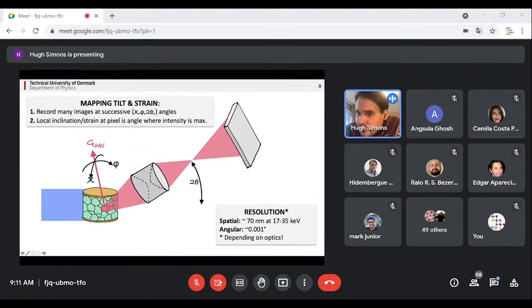And right now we have a spatial resolution of something like 70 nanometers at between 17 and 35 keV. And we have an angular resolution of about 0.001 degrees. This all depends on optics, but I would say our spatial resolution is good enough to see many small features, but our angular resolution is really quite exceptional. So in many cases, it's in excess of, for example, what you can get with TEM.